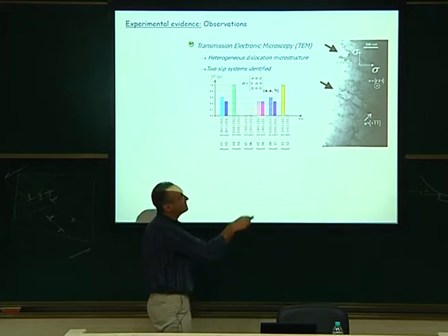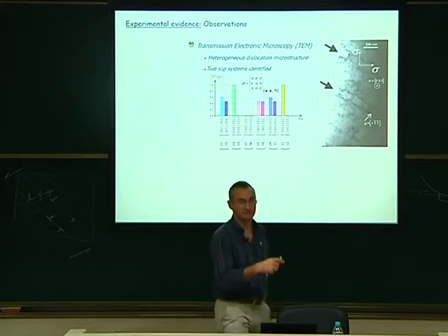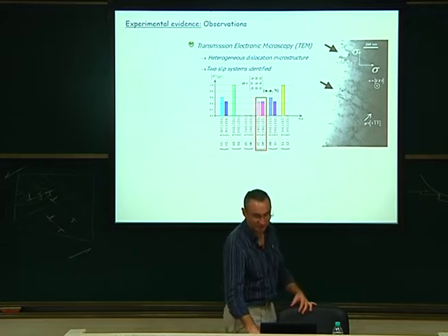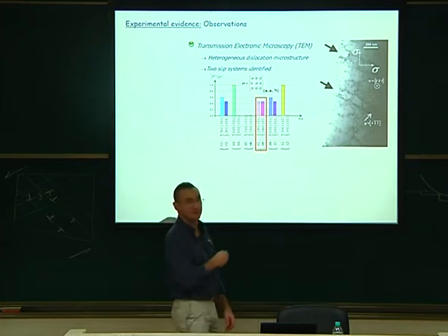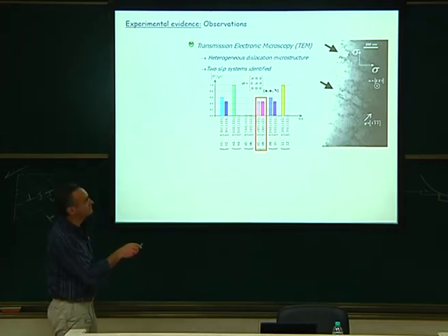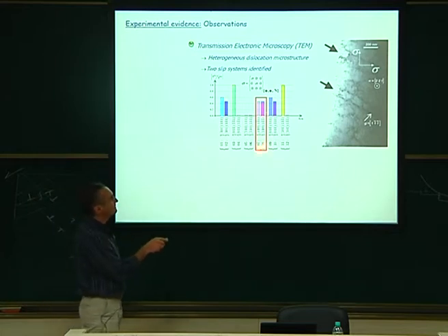And the dislocations he observed in the TEM, he did the g dot b analysis, and he was looking at their character, and we found that they belong to those two slip systems here. So there are two families of dislocation, mainly. You have a few others, but those are the main dislocations on systems number 7 and 8.